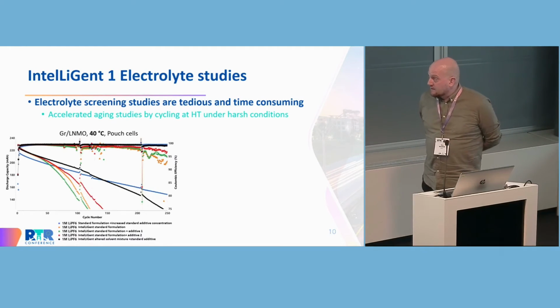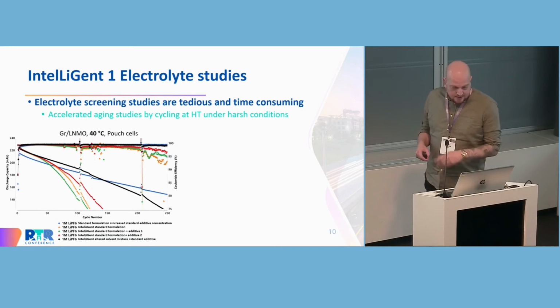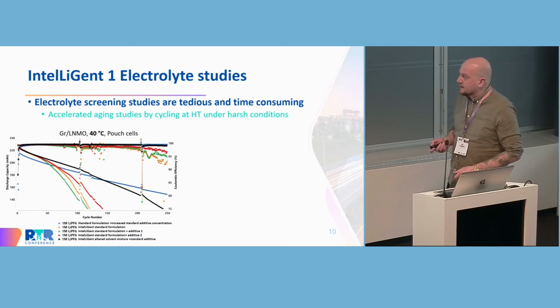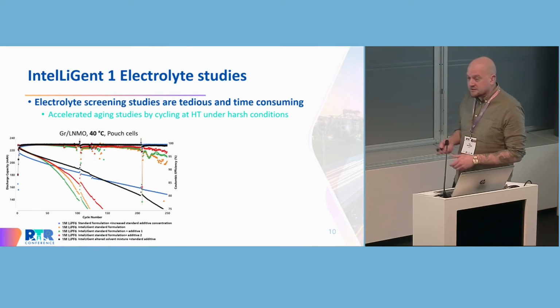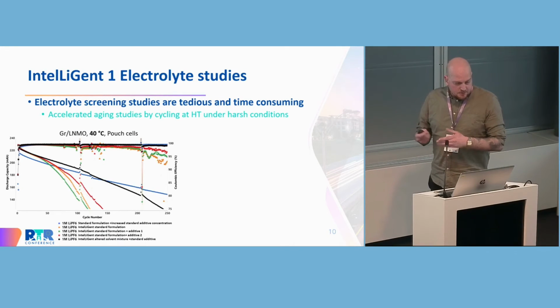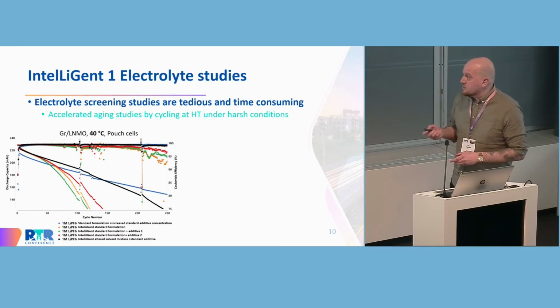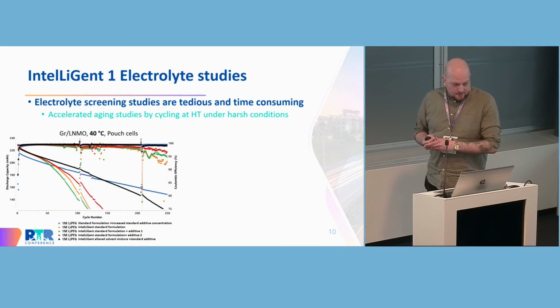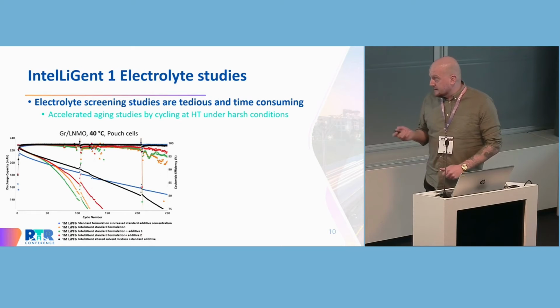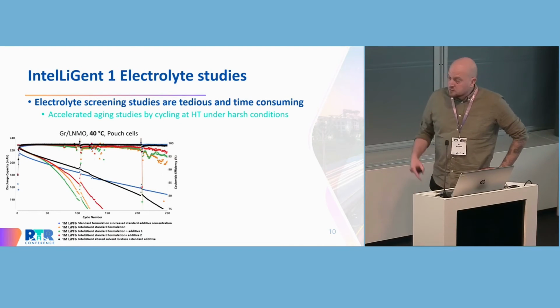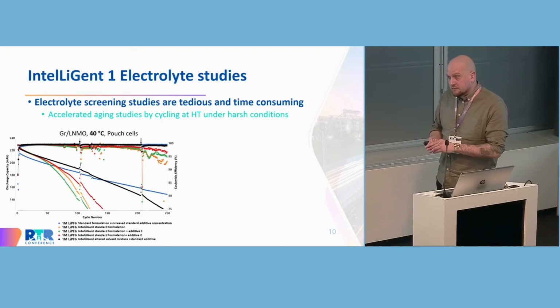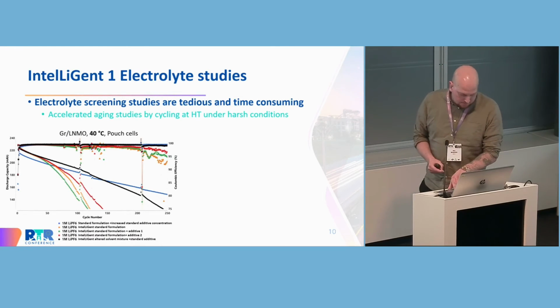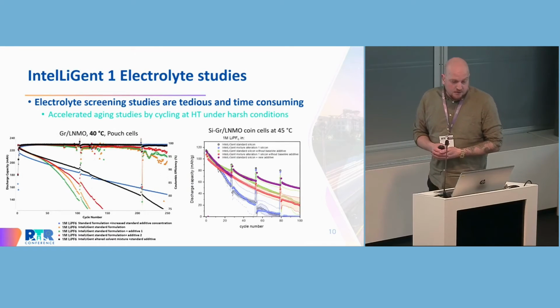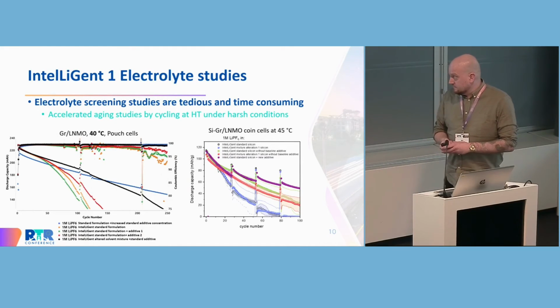The first one is on graphite LNMO pouch cells that were cycled at 40 degrees C, and here's a lot of different colors. The thing that I want to highlight now, in orange we have what we called our intelligent standard, our first electrolyte generation that we based our results on. And then in blue you see when we increased the additive to this, which had a profound impact on the cyclability. However, we had a slightly higher impedance in the cell and slightly lower initial capacity. And also in black, which is still basically the same electrolyte, we just replaced one of the solvents by another one. We saw a much higher cycle life. So there is a lot to learn still. But of course, we also look at the silicon graphite LNMO cells. And this is some relatively new results.